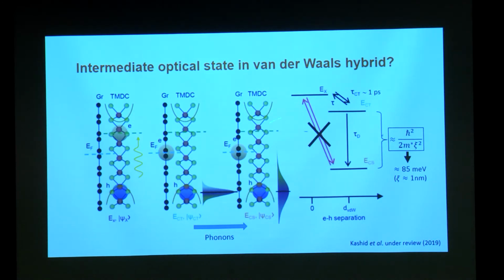An intermediate state where the electron is in the Fermi energy of the graphene and the localized hole. So the difference between the two energy states is approximately ħ²/2m*ξ², where ξ is the localization length of a typical exciton in the chalcogenide layer. And this energy difference is approximately 85 millielectron volt. So is this hypothesis correct? Let us have a look at it.